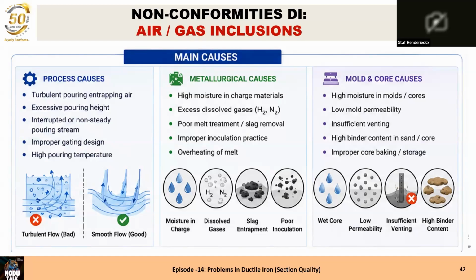If the slag is not removed very well, slag can be the reason that some more gas or whatever is initiated and stays in the casting. Improper inoculation practice is a little bit less likely, but can do it. And overheating of the melt is, of course, mainly the reason for gas.